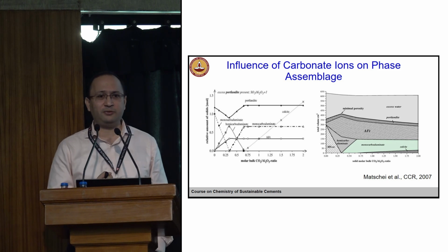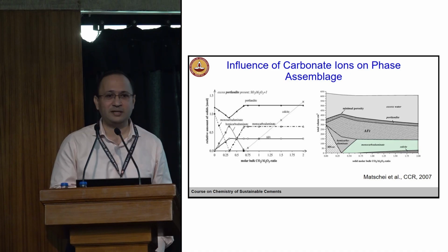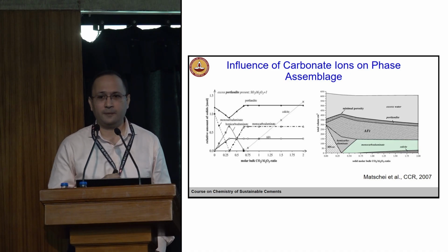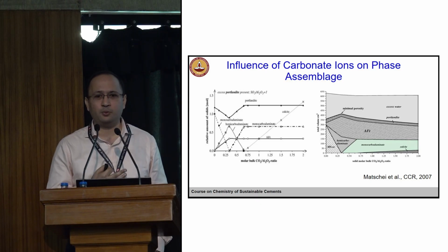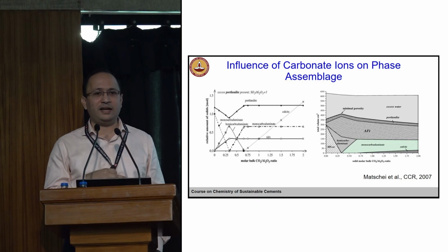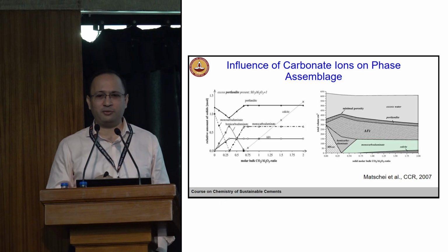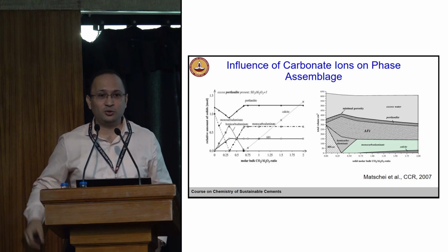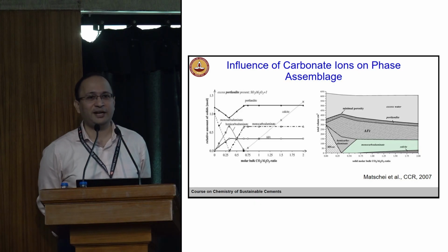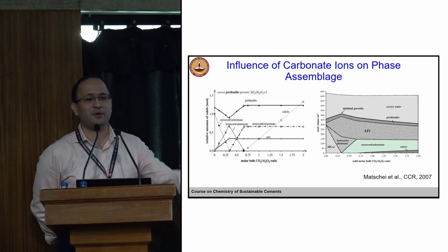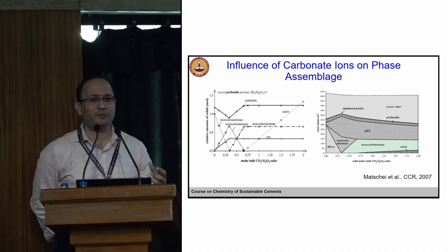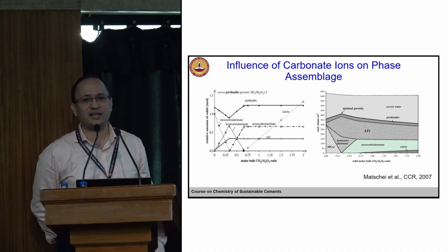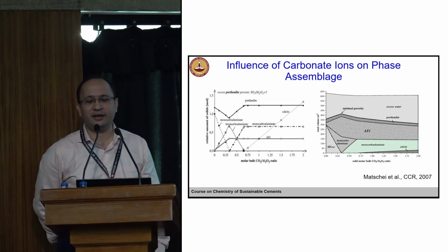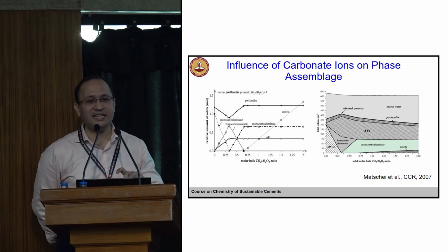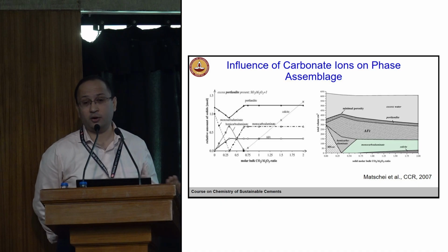You form AFt phase, and once gypsum is depleted, it converts into AFm phase. So if you examine your hydrated Portland cement at later stages, you will find monosulfate. So there is a transition from AFt to AFm, and we know that phase is also responsible for sulfate attack, external sulfate attack. For example, if you have sulfates coming from outside, that AFm can react with additional sulfates and form AFt. That is a reaction which increases the volume, an expansive reaction. So a lot of issues.